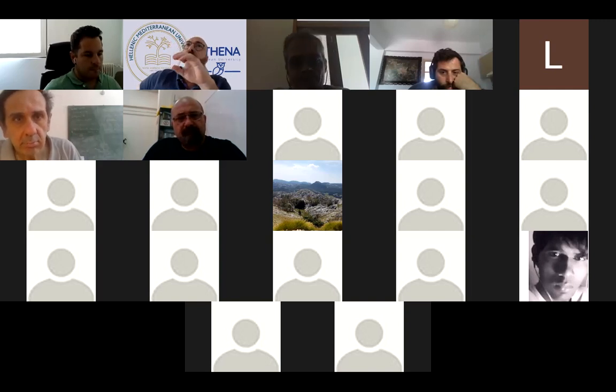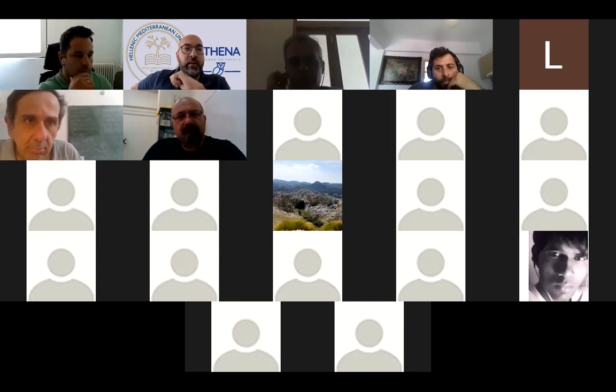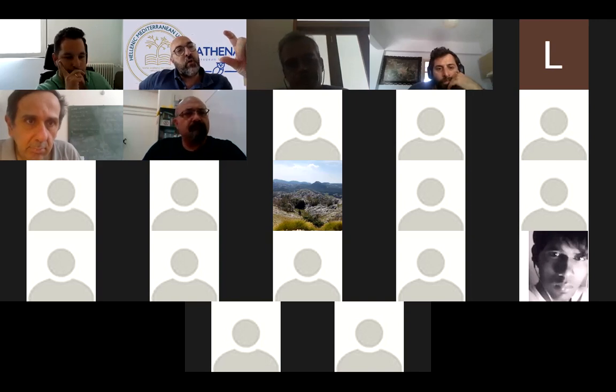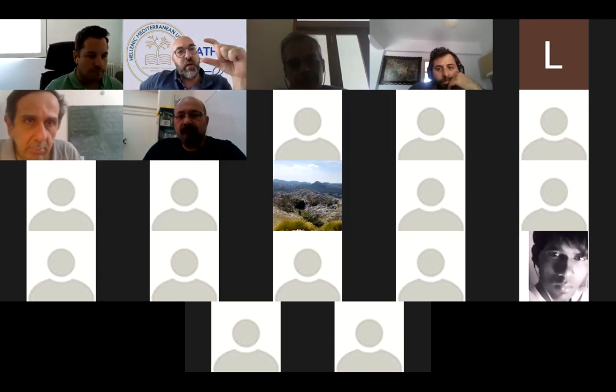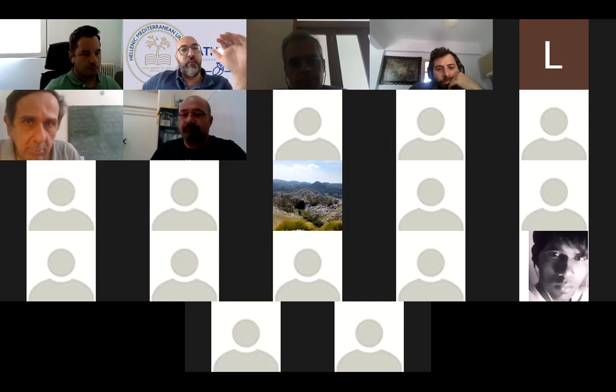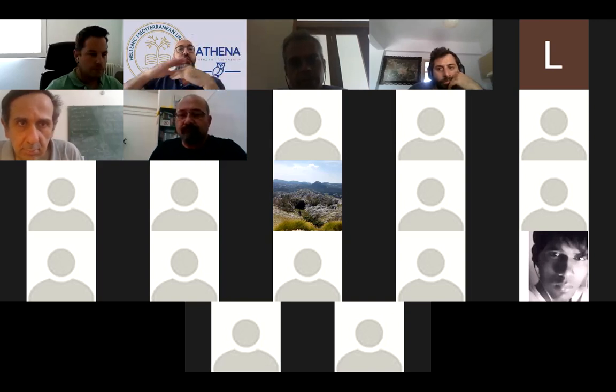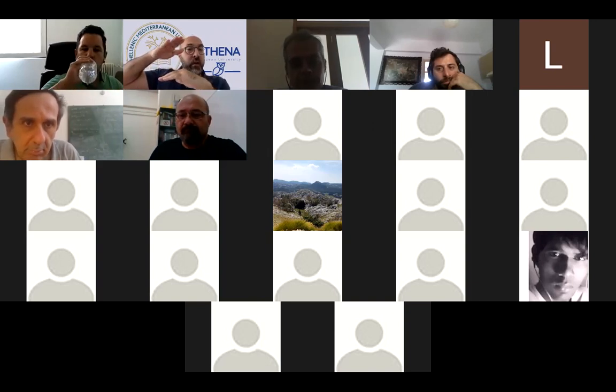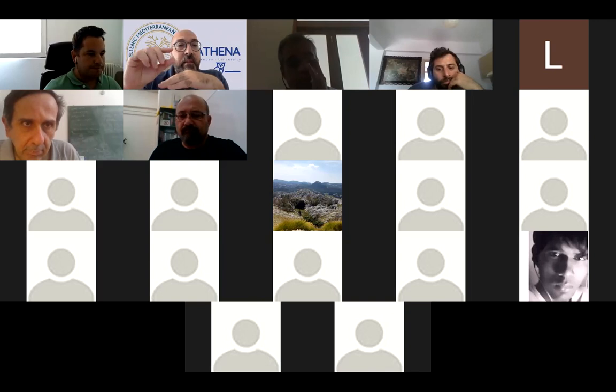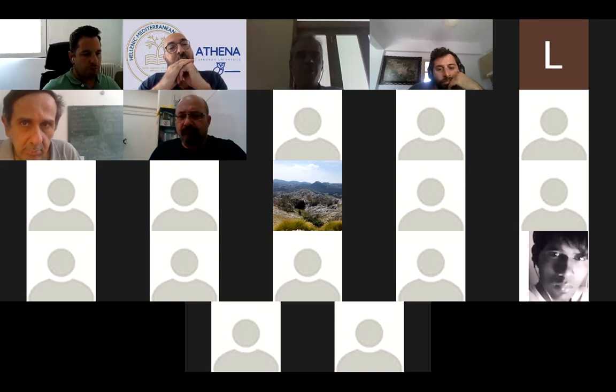Sorry, Luis, and then I will give the floor to my colleague, Dr. Rodakis. I was not talking about the full length needed to observe this vertical change of polarization, but about the distance between the layers, because as you can see, you have a gradual rotation of the molecule. So the minimum distance I was talking about is between the layers. Imagine that you place an interface between two layers. This will have an effect depending on the thickness of this interlayer, the effect of having a selectivity.